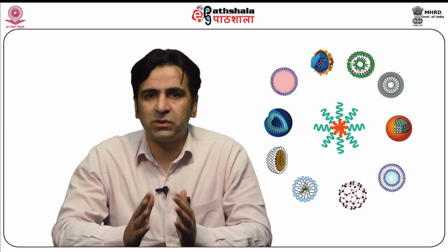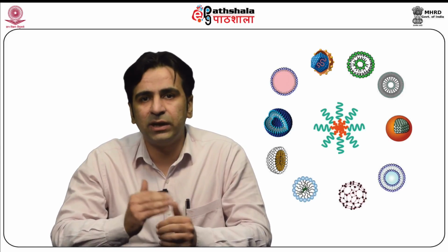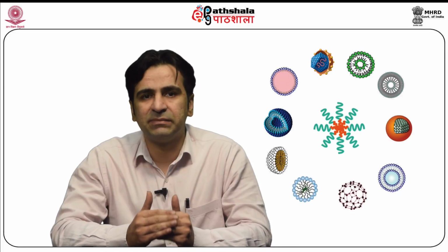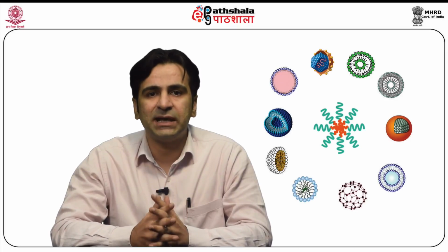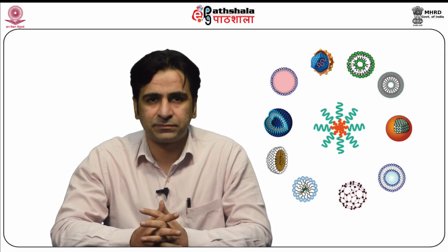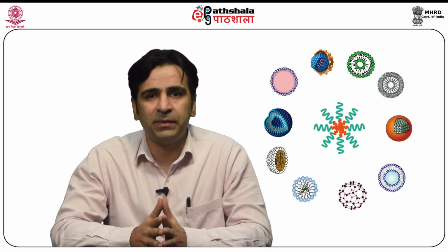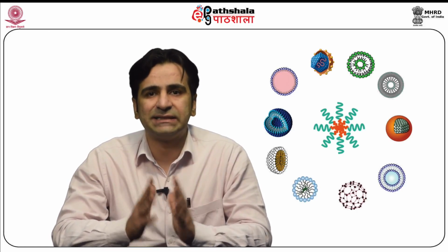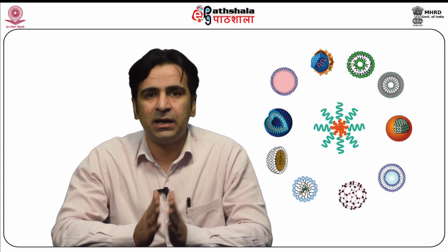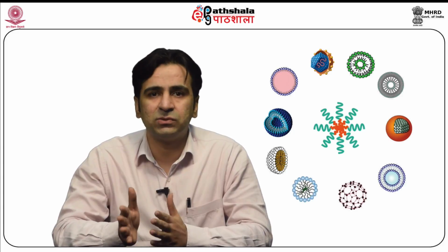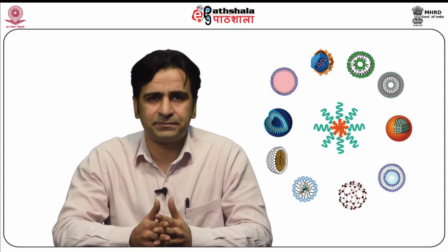The radioactive glycine is conjugated with the microsphere by using a linker, and the radioactivity of the conjugate is measured using a liquid scintillation counter, from which carboxylic acid residue is correlated. Similarly, surface amino residue is determined by radioactive C14 acetic acid. This is an indirect method of determination. Initially, carboxylic acid residue is measured through the scintillation counter, and then amino residue is linked indirectly.